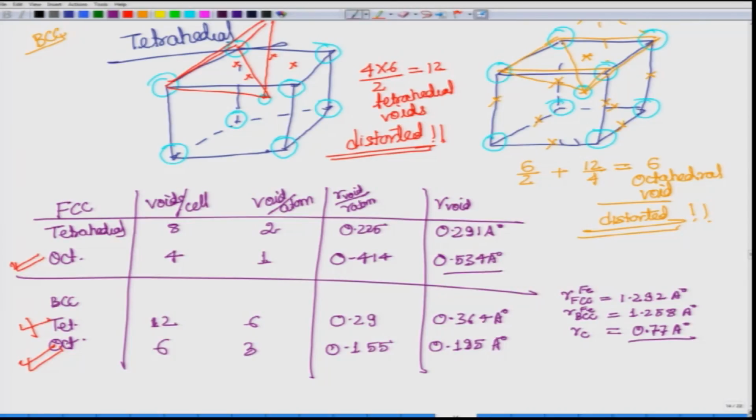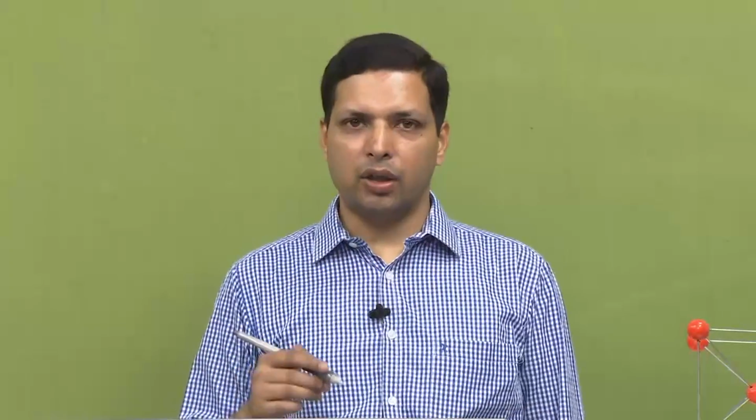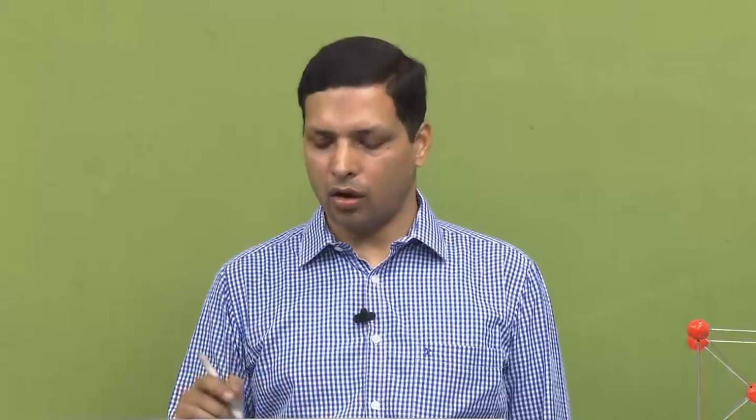The presence of these atoms in that place leads to lower free energy, and therefore the carbon atom goes there. All the strain energy that is caused is included in the enthalpy of formation, because some amount of energy will have to be put into the system to accommodate that strain. And in spite of all that, because of the configurational entropy, the system is able to get lower energy by the addition of this carbon atom. So this is something that would appear quite counterintuitive on first encounter.